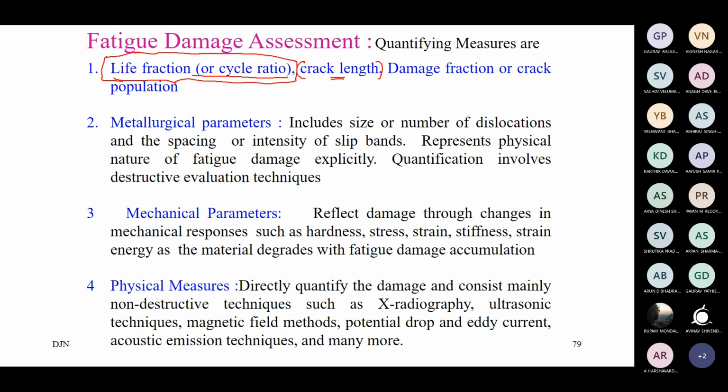The NDT technique available is XRD with the special attachments, or else we have destructive testing, either the bending method or hole drilling method, but it is destructive. It will not serve the purpose in the practical scenario. So XRD method is the best one, but implementing in the practical scenario for continuous monitoring may not be a right option. Therefore, it has to be planned for certain interval duration.